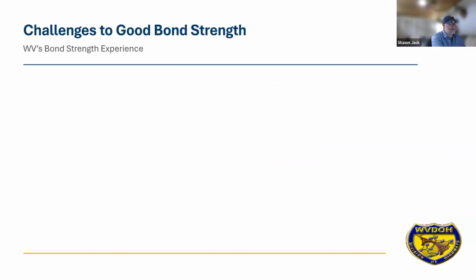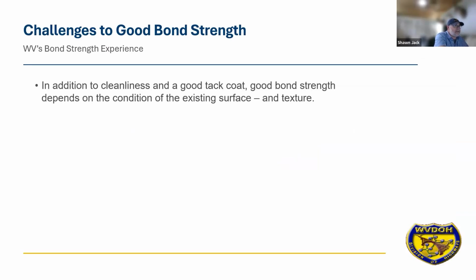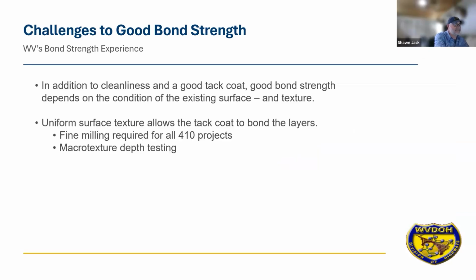So what are some of the challenges that we see? There are always a few challenges that we look to overcome. Randy talked about the importance of cleanliness and good tack coat practice. We also want to consider the existing surface condition and the texture. So we know that a uniform surface texture allows for better bond. And as a result of that, we require fine milling. We require fine milling for all 410 PWL projects, and we require macro texture testing to make sure that we're getting what we pay for with the additional expense.